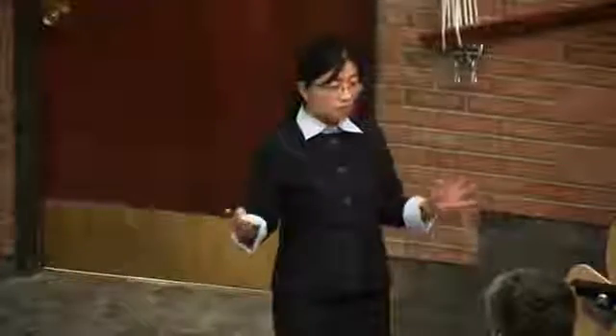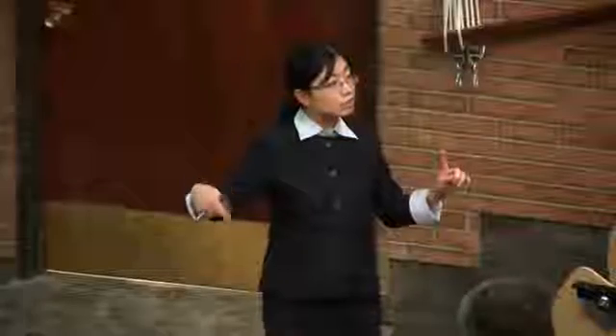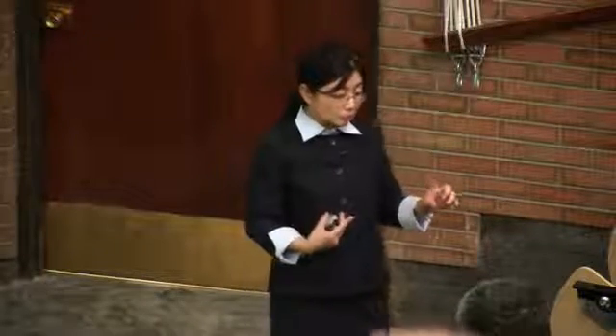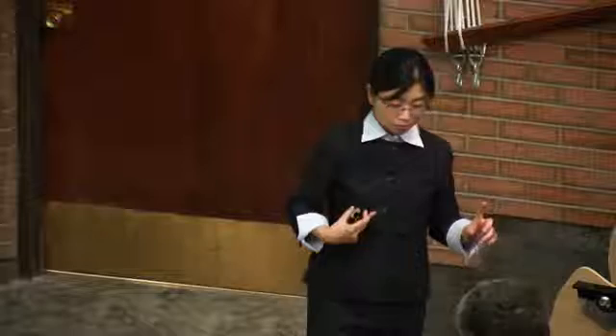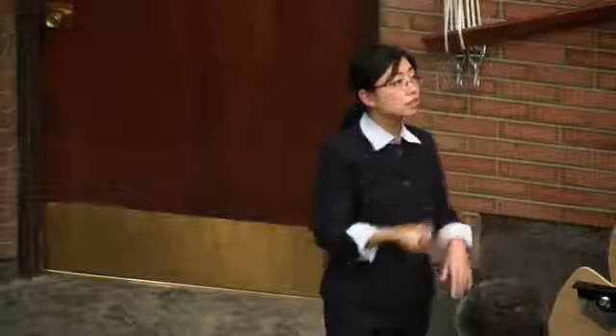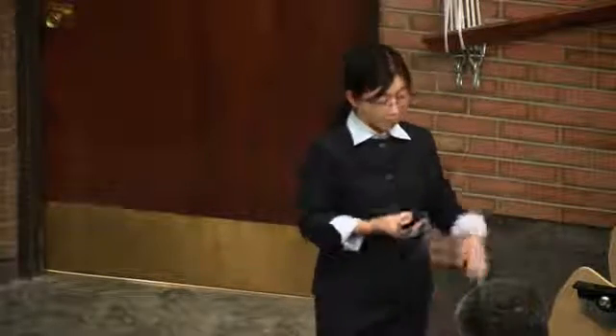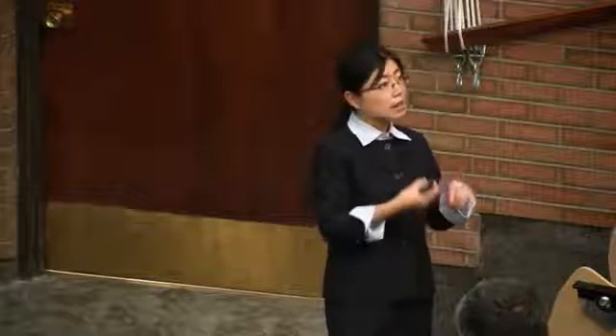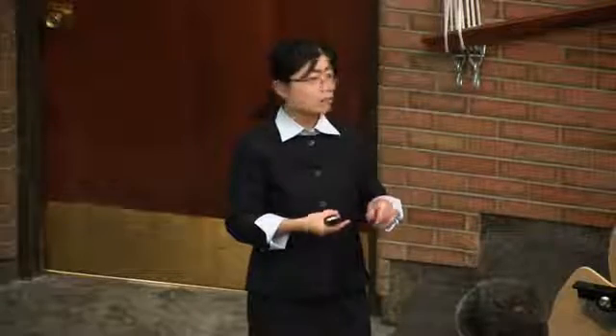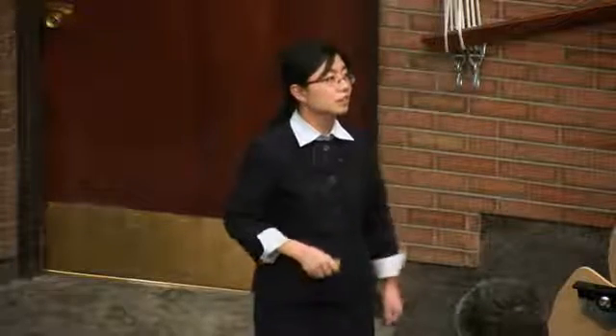Could it be dipolar coupling? Yes, between the electron and the hole. If they are spatially apart, it's a dipole-dipole interaction. But yes, what we measure, what I said as the microelectronvolt range, that is the zero field splitting. Basically, the zero field splitting depends on the exchange coupling. It's some linear combination of spin exchange coupling in different directions.